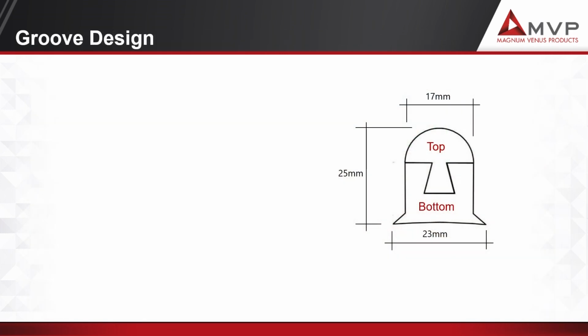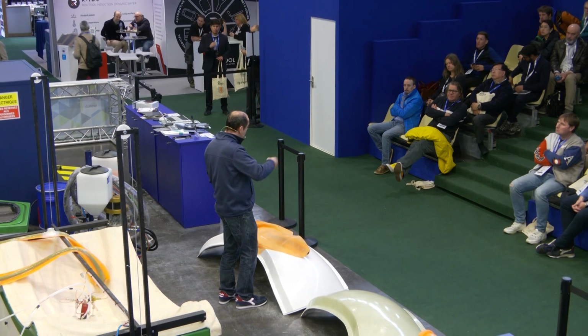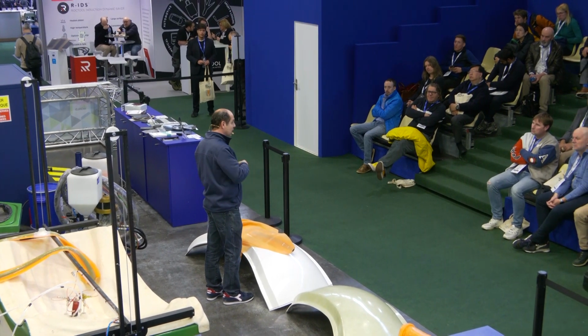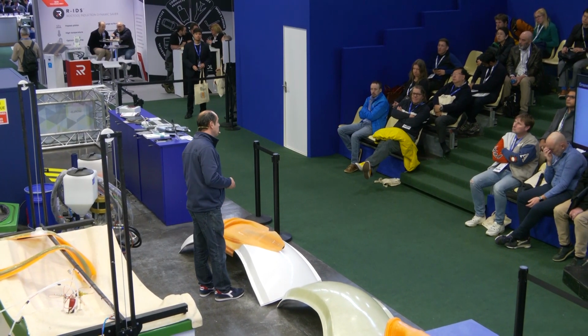So everything is based on the fact that on the flange of the mold, we have a groove. If you put a groove, which is a standard groove, you can do everything. You can do light RTM. You can do silicone bag. You can do SVB, which is plastic and silicone. You can do fast flow light RTM. So our recommendation, when you make a mold for closed mold, put a groove on the mold. Like that, after it, you can decide about the process. Everything will work if you have a groove on the mold.